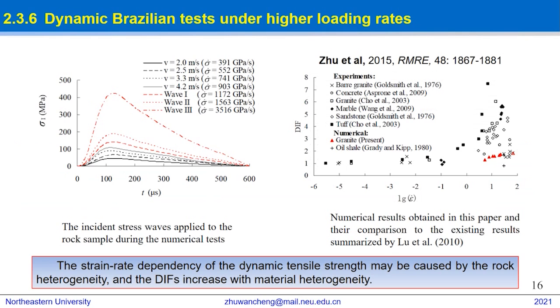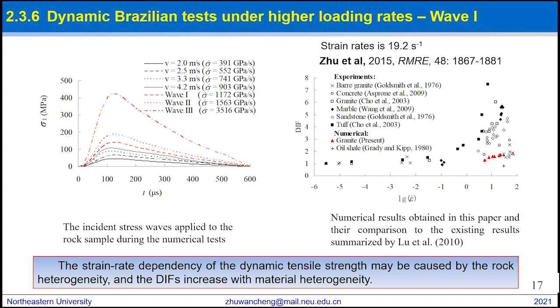Numerical results obtained in this paper and their comparison to the existing results are summarized by Lu et al. Our result indicated that the strain rate dependency of the dynamic tensile strength may be caused by the rock heterogeneity, and the DIF increases with material heterogeneity. Under the impact of wave 1, the damage in tensile mode, shown as red color, initiates firstly at the center of the disc, and then the scattered damaged area in tensile mode is distributed mostly along the horizontal diameter.